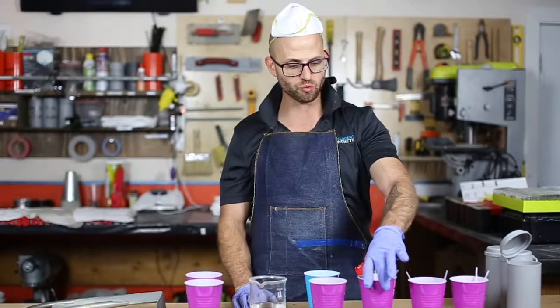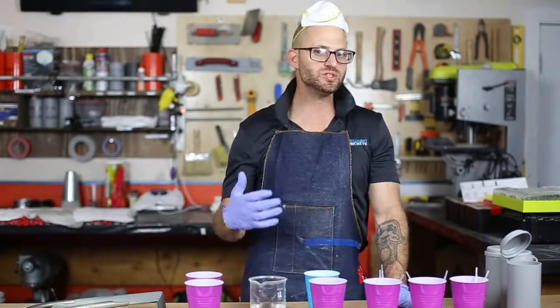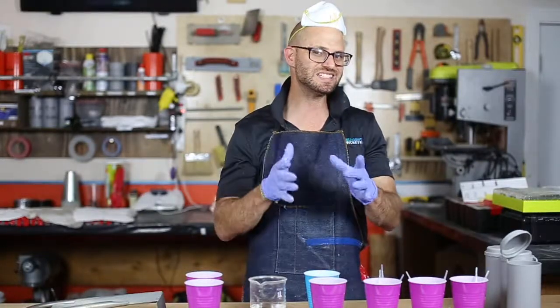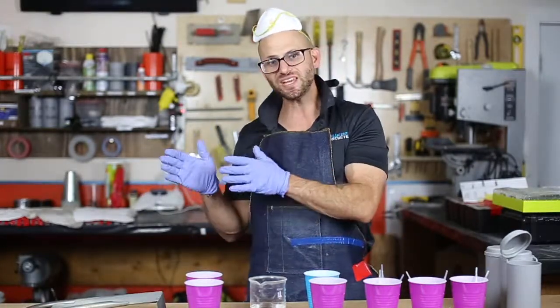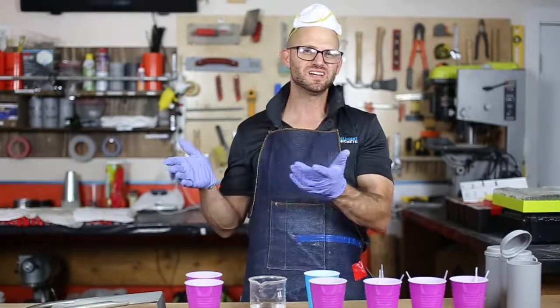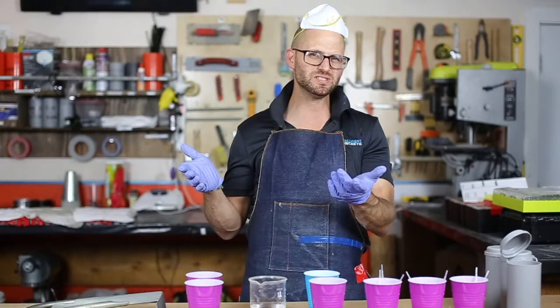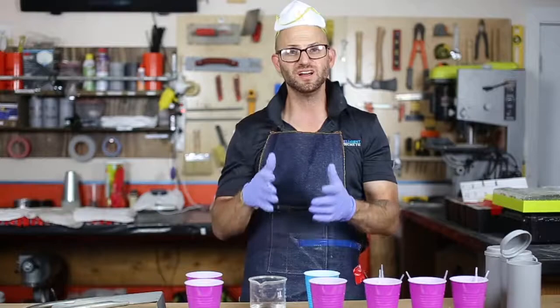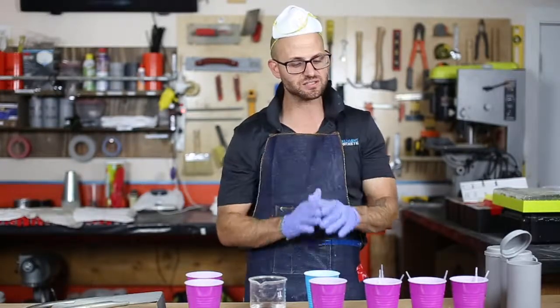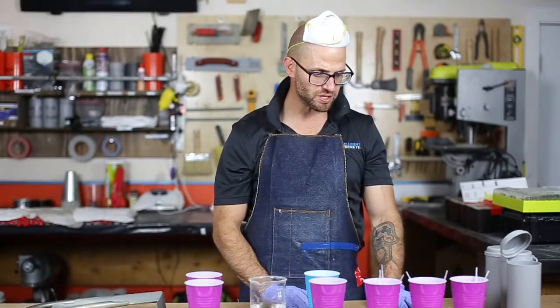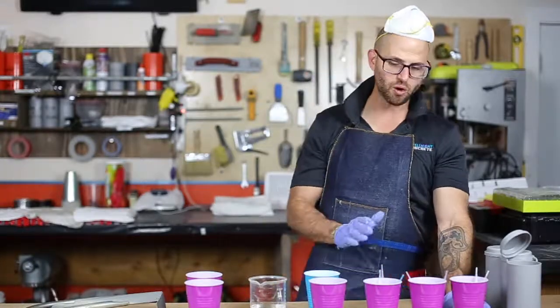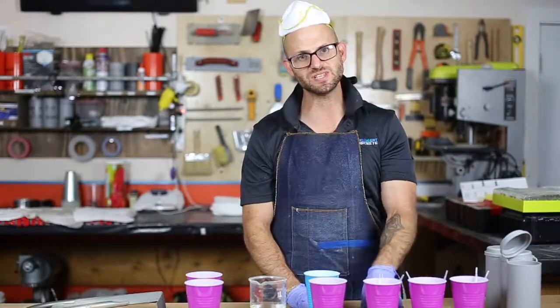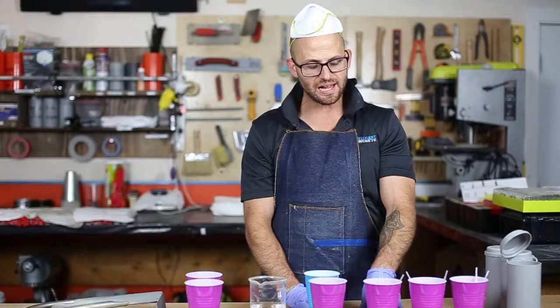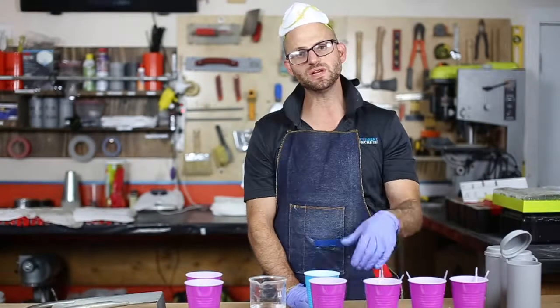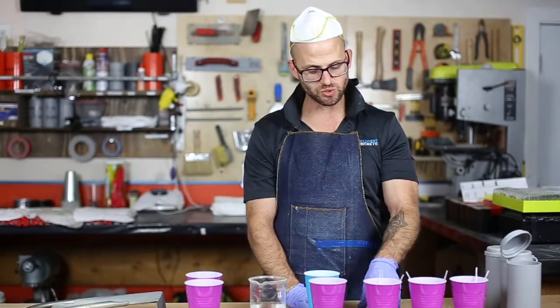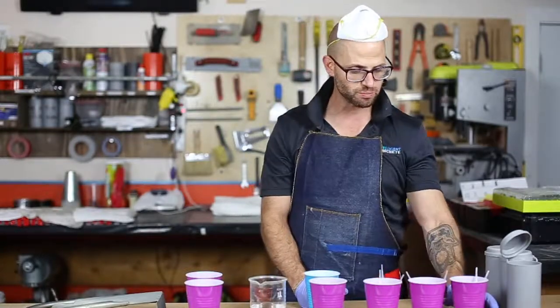I've also got some corrosion inhibitor here. We're using that to boost up our strengths. I'd like to see if we can make our 28-day strength, which was, I believe, 5,300 PSI, somewhere around there. I want to see if we can make that in 7 days. So we're going to be using a small bit of an accelerator. We're also going to see some corrosion resistance from this as well. It's a pretty cool admixture when you use it at higher levels. It gives you that accelerating property.